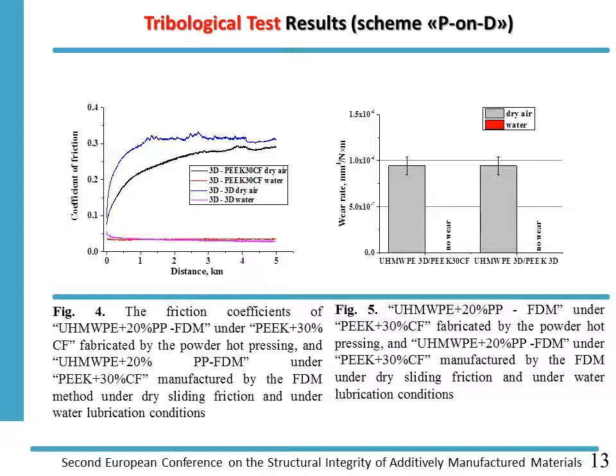The next slide illustrates the data on tribological tests. We used a pin on disk scheme, and on the left you see the graphs for friction coefficient. We tested under dry sliding, and also under water lubrication. You see that under water lubrication the friction coefficient is much lower. But what is of particular interest is that the specimen prepared by fused deposition modeling also possesses a low friction coefficient in contrast with hot pressing, but here it is nearly the same.